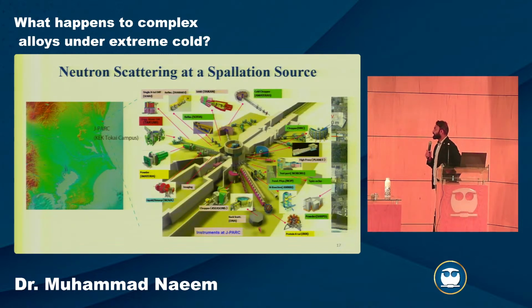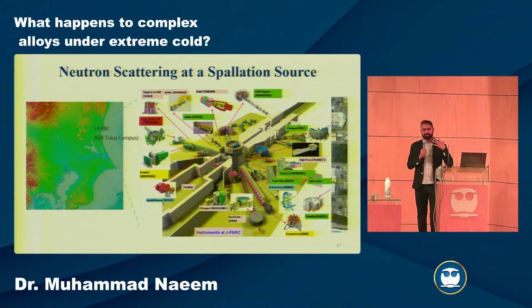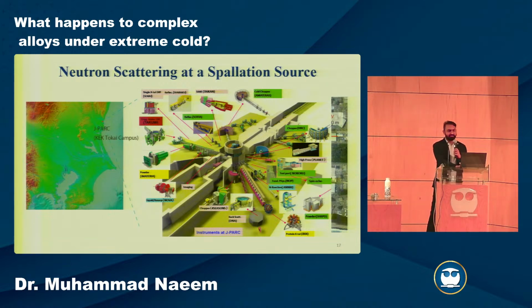As I mentioned, we can get different kinds of information from the sample, so they have different kinds of beamlines, or instruments, to do that. Some are suitable for, for example, precipitates in superalloys, where we can use small angle neutron scattering. Others can be used, for example, for high pressure; geology people mostly use this one. Then there are others as well. But the one which I was using is here, in red. It's called TAKUMI, which is an engineering materials diffractometer.